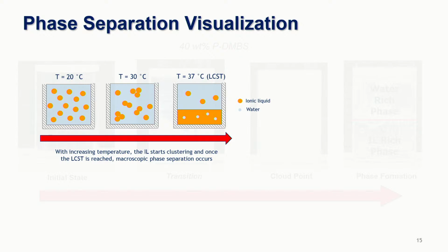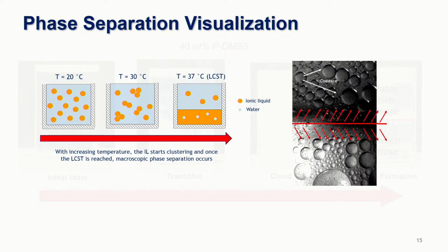And so what we think is happening in the process is, the ionic liquid is dispersed within the water phase. As we increase temperature, the ionic liquid starts clustering. So that's what we're showing here. You form these clusters. And then finally, when you hit that critical temperature, you have created a sufficient number of clusters that allows you to now just form that second phase. And we've seen some evidence of this.